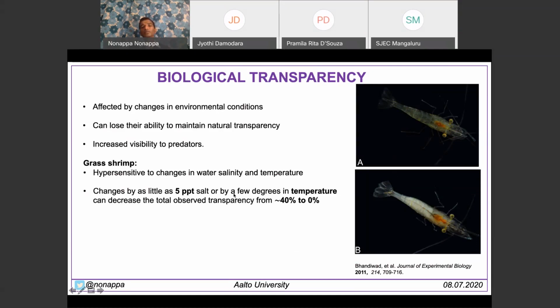So if you slightly change 1 or 2 degrees Celsius, the transparency goes from 40% to 0%, it will change rapidly. And this is not good. So this is also difficult to maintain.